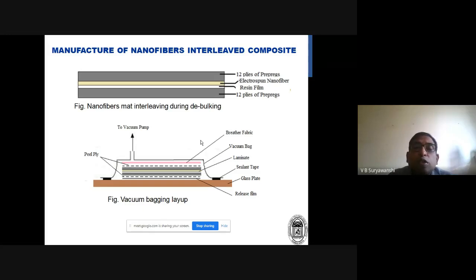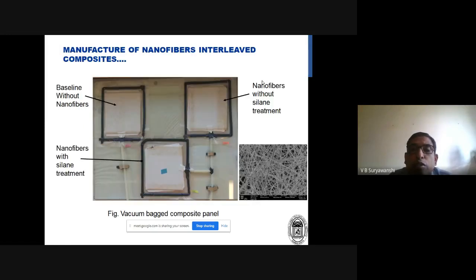In another application, what we did, instead of chopping those fibers, we simply put the electrospun nanofiber mat. The mat is nothing but like a cloth, correct? So we deposited it on the collector plate, and that is how we made a nanofiber mat. If you put it on the resin film, what will happen? These two things will join together, and then there are the various prepregs. Prepreg is nothing but the one which has resin and fiber both. So in between the two layers, as we had mentioned earlier, the composite is generally weak. So if you can reinforce that region with the help of the nanofibers, we should be able to get improved performance. So how do we check the performance?